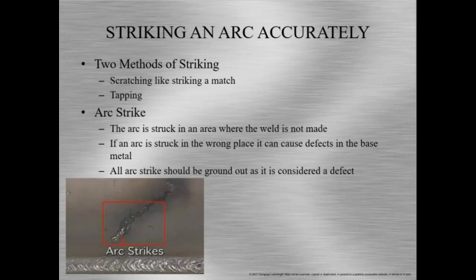The other thing is called arc strike. Arc strike is where the welder strikes the arc, but not in the area where the weld is made, okay? So if we see here, here's our nice little pretty weld, and here's our arc strike. Now, if an arc is struck in the wrong place, it can actually cause defects in the base metal. So this is one of my big pet peeves as a welding inspector. All arc strikes should be ground out, as it is considered a defect, and it can be a reason for rejecting the weld or even failing a welding test. So this is really important to make sure that you know and are accurately striking an arc.